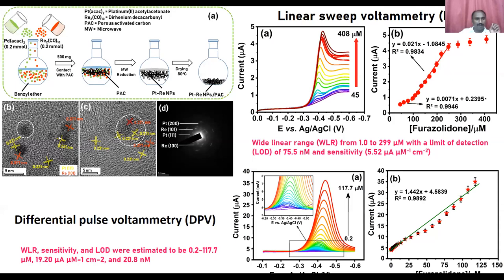The yellow color indicates platinum, and the red color indicates the rhenium nanoparticle. You can see the very, very small size, nearly 2 to 3 nanometer range, of rhenium nanoparticle deposited on this porous activated carbon. And this composite is further studied for the sensing of furazolidone by linear sweep voltammetry and differential pulse voltammetry. We can study the concentration range and make the plot. And from this plot, we can calculate the sensitivity and the limit of detection and the linear range of sensing molecules.